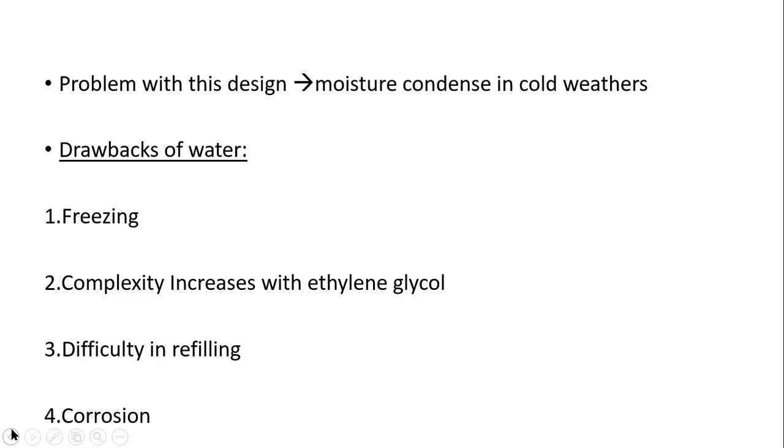The tubes are filled with water and then drained. The water is drained out at night, so some moisture will be present in the tubes. If this moisture combines with the oxygen in the air filling the tubes, it increases the rate of corrosion. This corrosion problem can be minimized by using copper tubes, but it is somewhat costly.